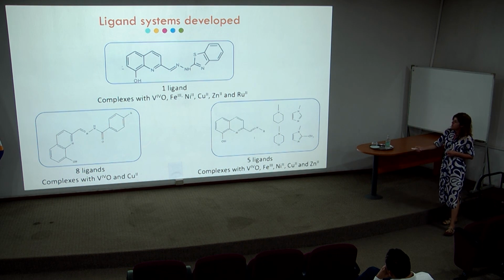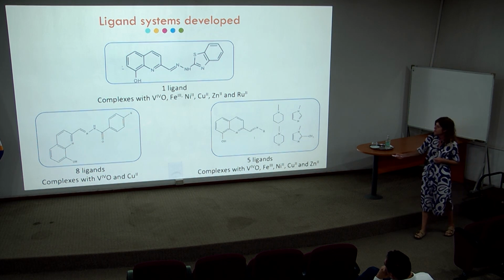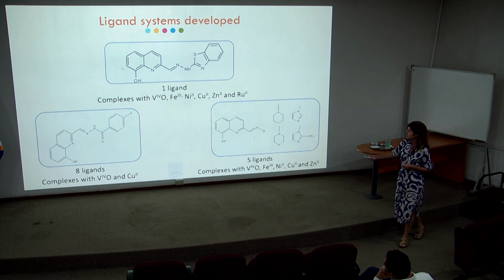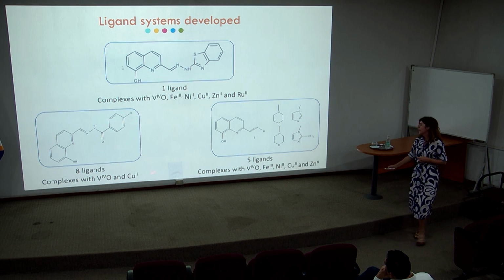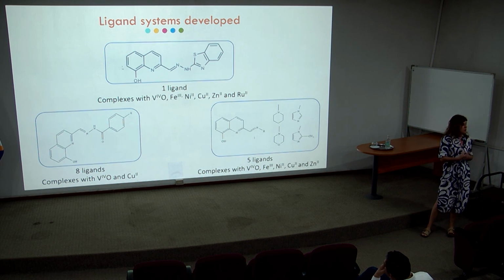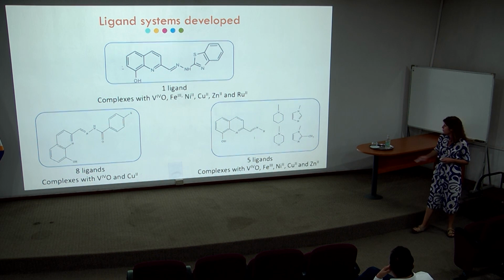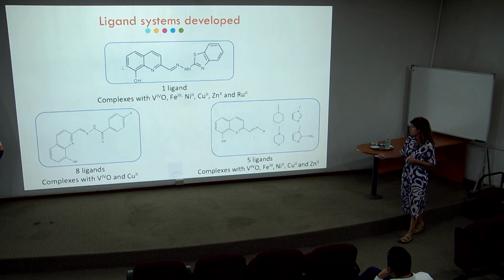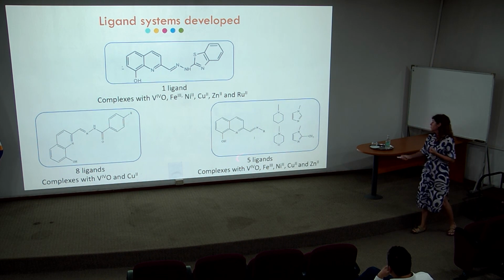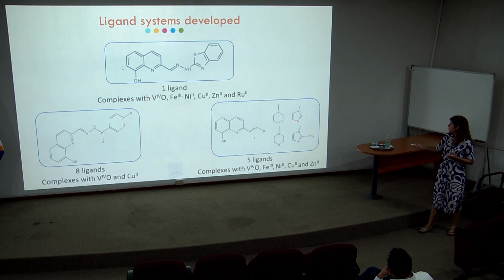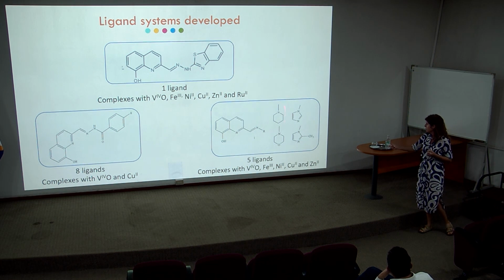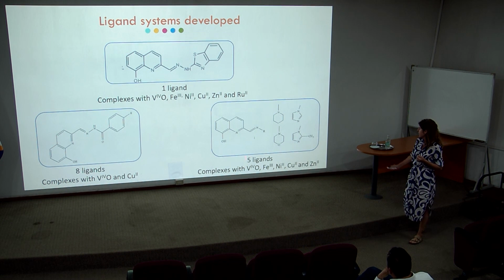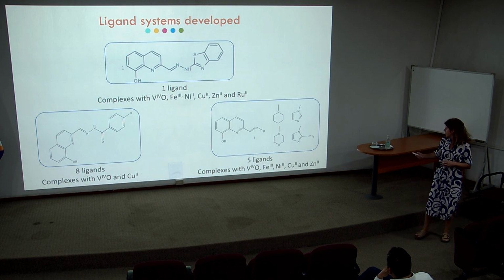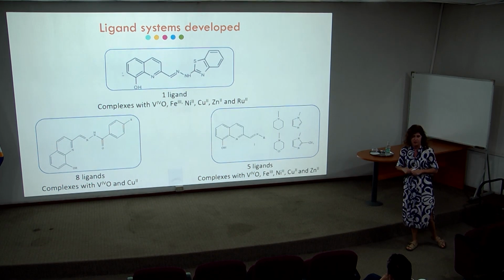Another system in which we obtained 8 different ligands with different substituents here in this para position, and as metal ions we chose vanadium-4 and copper-2, and this system which are Schiff bases in which we produced 5 ligands, although I'm going to focus on the ones containing morpholine and piperidine, and we complexed it to a series of metal ions. The work with copper and zinc has been published.